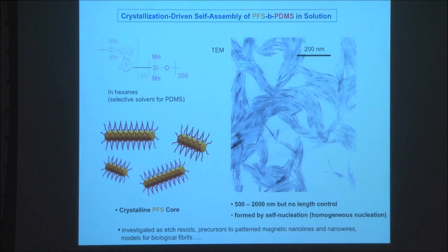And in this process, what you can show is that the core of these micelles is crystalline. So here's a cartoon of these micelles. You've got the dimethyl PFS core in amber here, the polysiloxane in red. And you can show by X-ray diffraction and electron diffraction that this core is actually crystalline. And you can look at the spherical micelles that I showed in the previous slide where you had an amorphous PFS core forming block, and you can show that they're amorphous. So somehow the crystallization of the core forming block directs the self-assembly away from spheres to give you really well-defined cylinders, as you can see here.